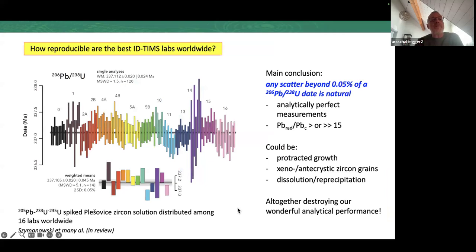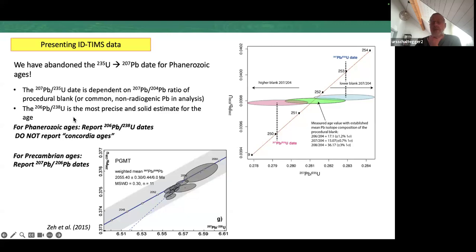And then a question which always comes, of course: how reproducible are the best ID-TIMS labs worldwide? And this is now easy to answer because there is a paper now in review of the EARTHTIME consortium. So we produced a zircon solution from Plešovice, thousands of Plešovice grains which have been dissolved and then spiked with a single lead, double uranium spike. The reason why we only used one single isotope of lead is that we do not have enough tracer solution with the double lead isotopes. And we sent this out to a certain number of labs, and most of the labs got back with results. And amazingly, 120